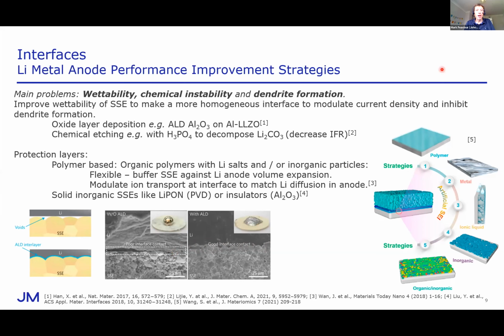In terms of tackling the issues of chemical instability, there are all sorts of protection layers that can be used. Often these are based on polymers, and sometimes they include lithium salts or inorganic particles to improve ionic conductivity. The great thing about polymers is that they are flexible, and so they can buffer against the lithium metal anode volume expansion, which may happen during electrochemical cycling. And they can also modulate the ion transport at the surface so there's no mismatch in ion diffusion around the anode interface, which is really important. There are other techniques as well. A lot of these protection strategies from reference 5 have been highlighted in this figure here, and I refer you to that reference for a thorough rundown on them.